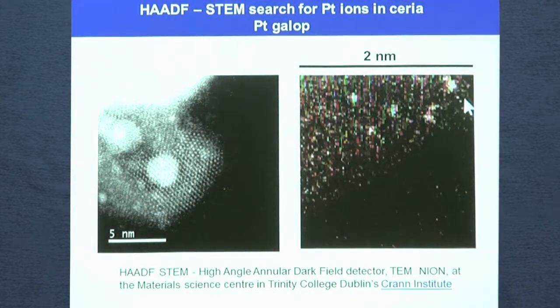Okay, and now of course we wanted to see if we really have the single atoms, which is not so easy, because the contrast between ceria and platinum is not very high. So we profited from the situation that maybe 2 or 3 months ago, one of the most performant TEMs worldwide was installed in the Material Science Centre in Trinity College Dublin, and we came there and we tried to look for